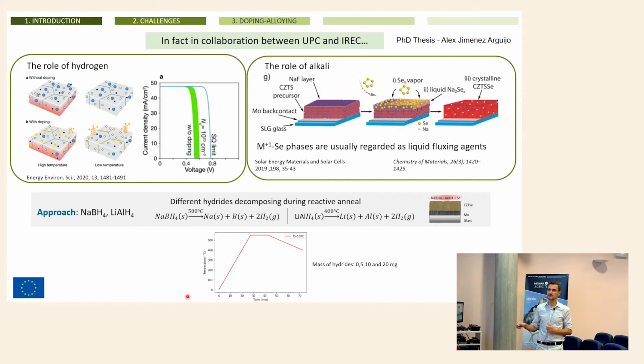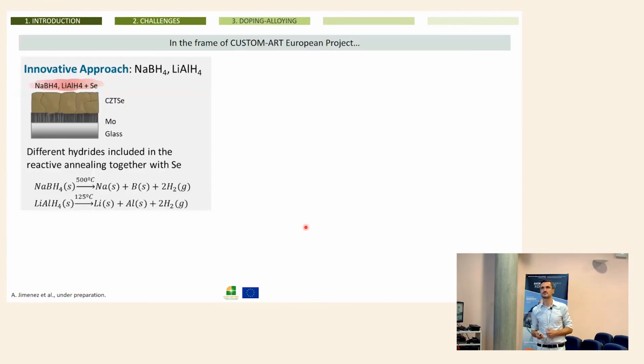During the formation of kesterite, this is the thermal treatment you need to synthesize and crystallize kesterite. Normally, you have to go up to 550, where the material reacts, is synthesized and crystallized. So what we do is, during these synthesis processes, we include these hydrides in the atmosphere, and we study the effect on the kesterite properties.